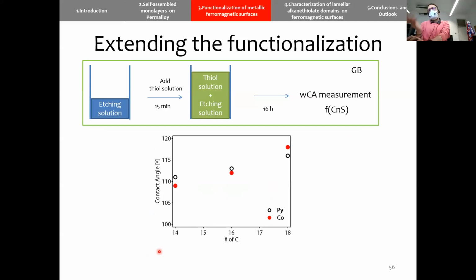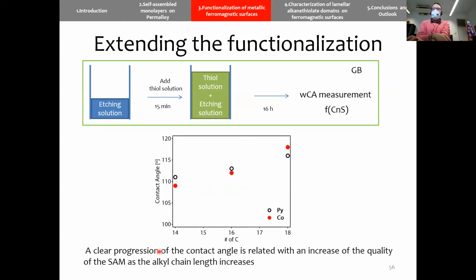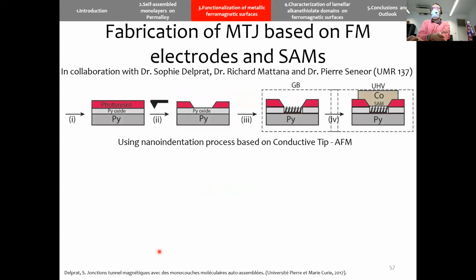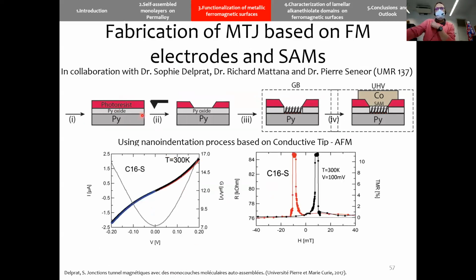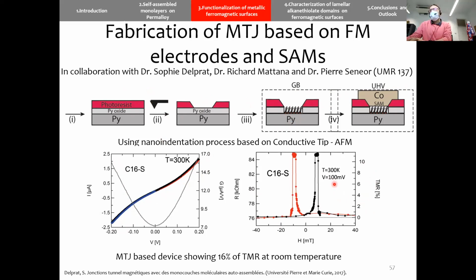We also tried this with the other families, and we see a clear progression of the angles. And we also tried to form the device. So in this case, it's a method developed in France, where using a conductive tip AFM they could make holes of a controlled dimension of 20 square nanometers by indenting this photoresist, and then they grew the SAM, and they completed the top part with the cobalt. So they perform at room temperature. We have a nice IV curve, and we also observe 16% of tunnel magnetoresistance at room temperature. Well, with not so high bias voltage, but at least, well, it's something.